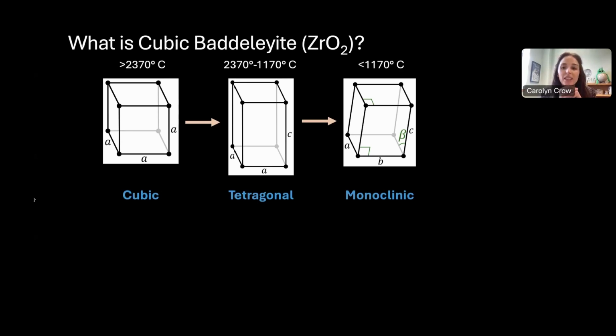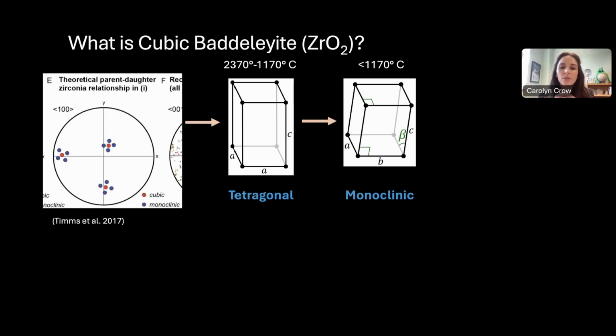The cubic structure of baddeleyite is not stable at room temperature. So even if it crystallizes in cubic structure, on the left, as it cools, it will shift into tetragonal structure by elongating along one of the axes, and then it will shift to monoclinic, okay? During all of these shifts, there are multiple ways. You can stretch when you're switching to tetragonal, you can switch along various axes. When you're switching to monoclinic, you can shift in multiple directions.